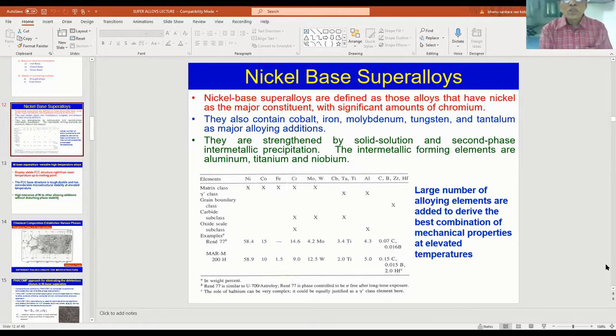These intermetallics are those which I referred to earlier as gamma prime and gamma double prime. If they are not properly controlled, these elements will contribute to some undesirable phases, which will reduce the ductility of the material. So control of composition is very, very important. The intermetallic forming elements, as I told you, are aluminum and titanium.